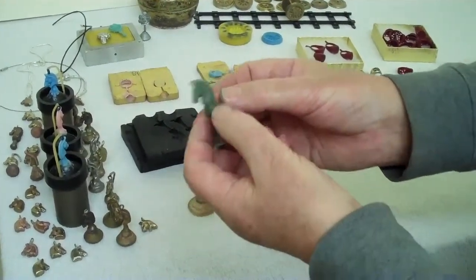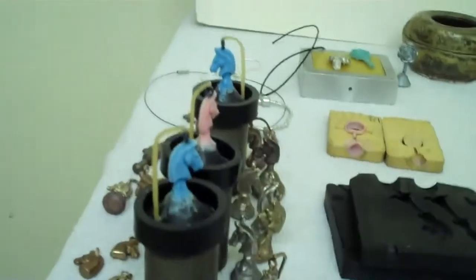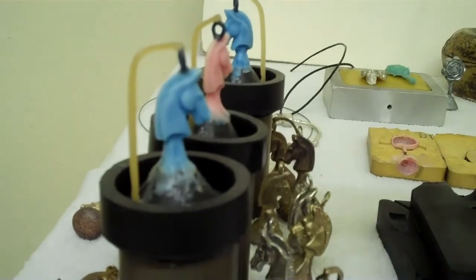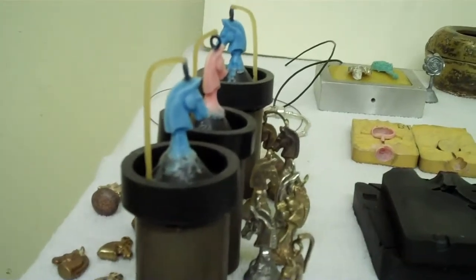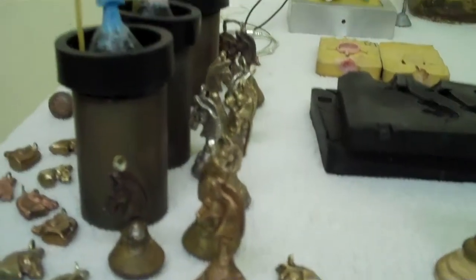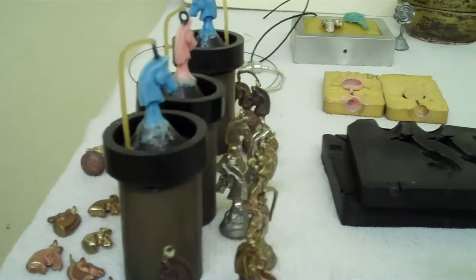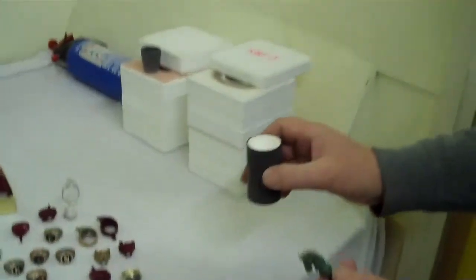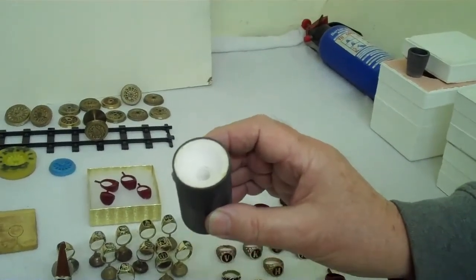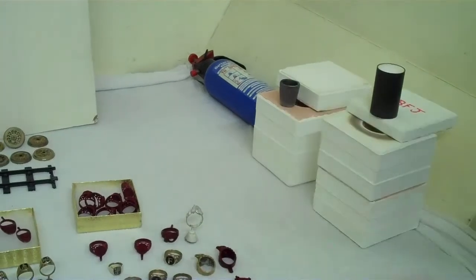We borrow the knight's head, and you can see here the knight's head has been sprued onto a rubber sprue base there. It had a dangling ring added and a vent coming from the bottom of the sprue up onto the top of the ring to allow the air to clear at pouring time. There's a flask put over that. It's invested, and the investment will be melted out, burnt out, and we'll finish up with a flask and a bone dry hot investment ready to take the metal that's been melted in the microfoundry.